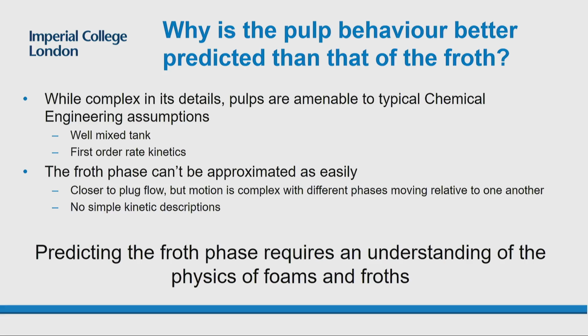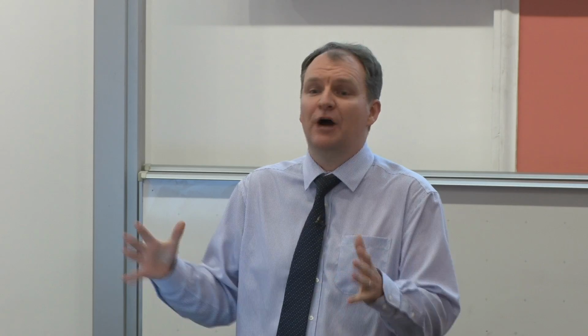So, first of all, why is the pulp phase better understood than the froth phase? The main reason for that is that you can apply standard chemical engineering type approximations to the pulp phase. At least to a first approximation, you can assume that it's well mixed, which means you can characterize it by a single concentration within it. It also obeys first order kinetics, at least approximately. That means how much material you pull over is proportional to how much is actually in your tank. You double your concentration, you double the rate at which you pull things over.